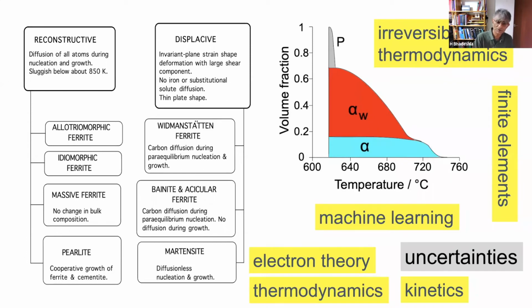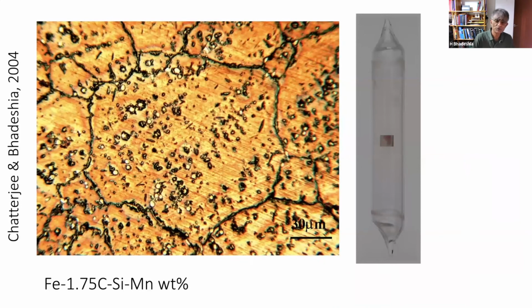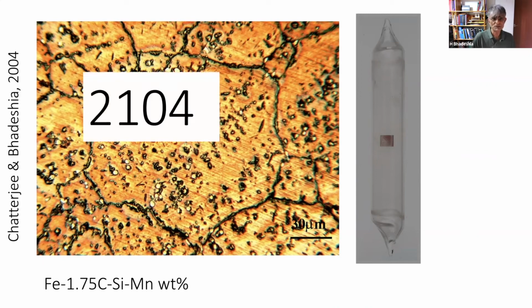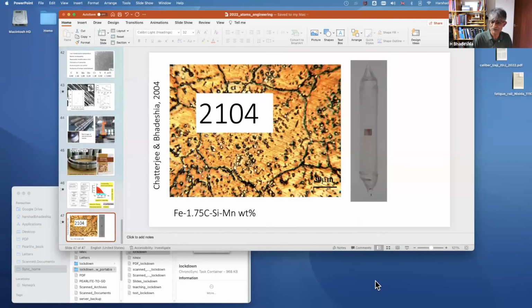Now, I mentioned to you that we could, in principle, produce bainite at room temperature, and it would take about 100 years. So we made the material, okay, in 2004, and there's a sample which is polished completely flat so that you would see surface upheavals if transformations happen, and is sealed in a quartz tube containing an inert gas, located in the Science Museum in London. And this experiment should finish in 2104. So it is very unlikely that I'll be around. So you need to tell this story to your children and their children to verify that actually we have produced incredibly fine plates of bainitic ferrite. So I'll stop there, and I'll be very happy to answer questions.